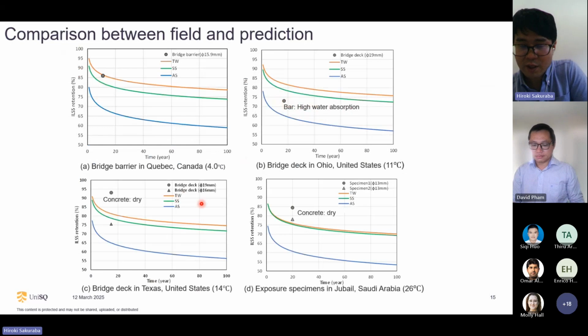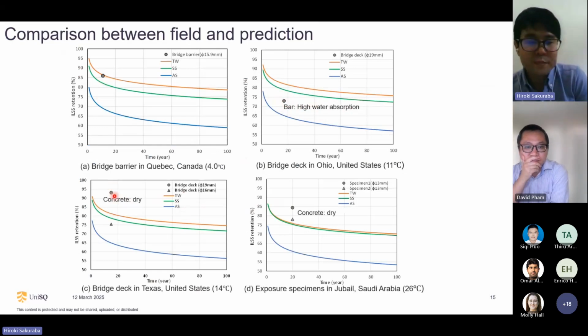For the other cases, the retention is relatively high. I believe this is because the concrete was in drying condition. If concrete is in dry condition, the alkaline environment can be milder. So that's why this field durability data shows relatively high retention.